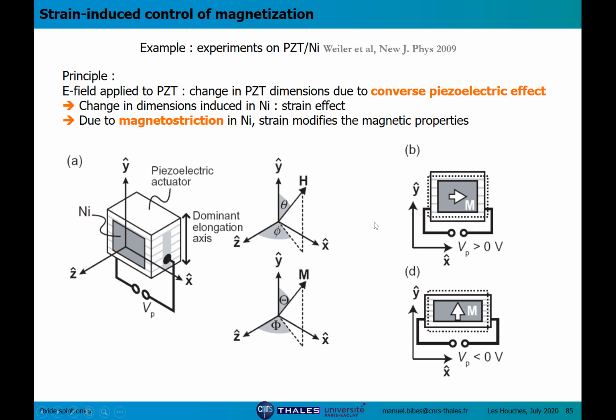Because nickel has a finite magnetostriction, when you apply a voltage to the piezoelectric, it will deform. And the nickel, which is attached to it, either directly deposited or glued with some composite or some epoxy, will also deform. This will induce some magnetoelastic anisotropy in the nickel that will compete with the other anisotropy. If the magnetoelastic anisotropy is strong enough, the easy axis of magnetization will switch by 90 degrees.